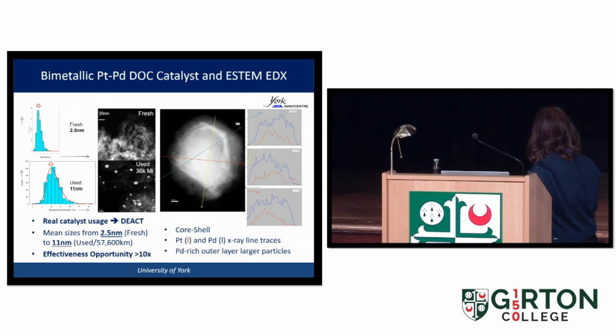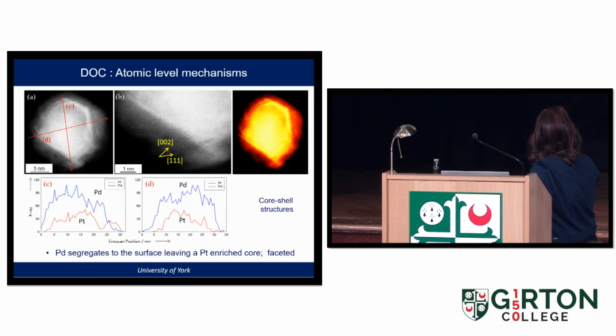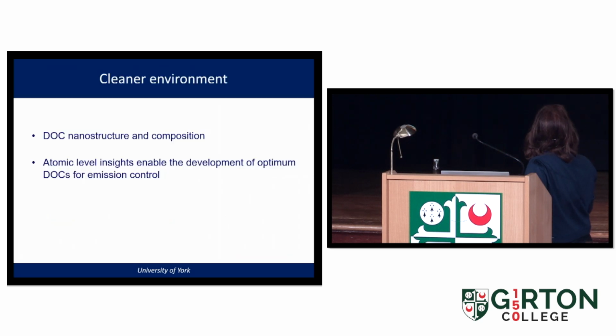And you can see in the next slide, very nice segregation of a species on this other metal. When you look at the colored picture here, you can see something has segregated on top. He used high precision chemical analysis to show that the segregated surface is actually palladium and the core is actually platinum. So we see that palladium is very interactive with carbon monoxide. These insights have given us the opportunity to develop optimum designs for emission control. That's what we are working on at the moment.